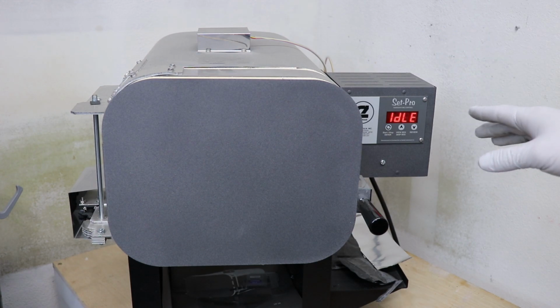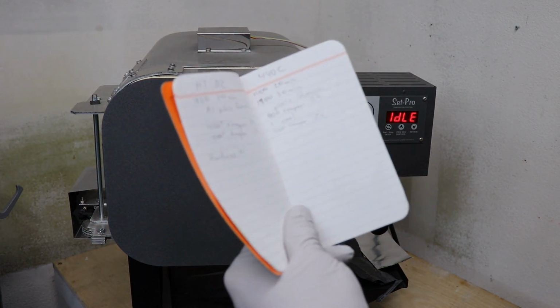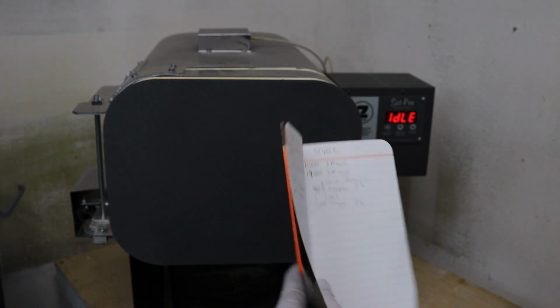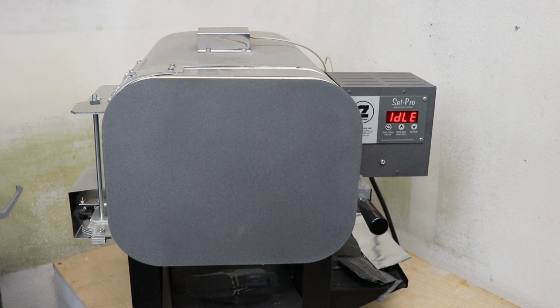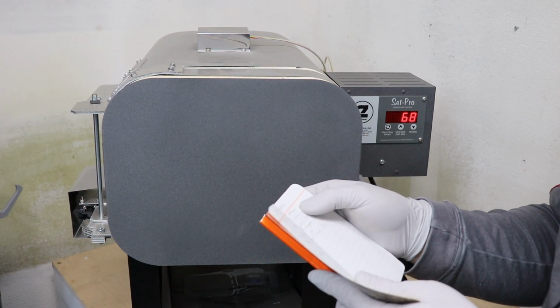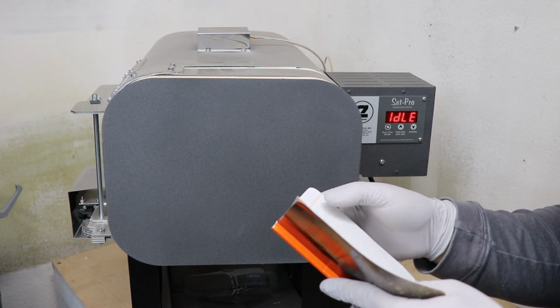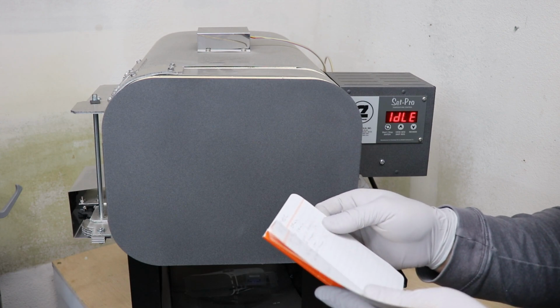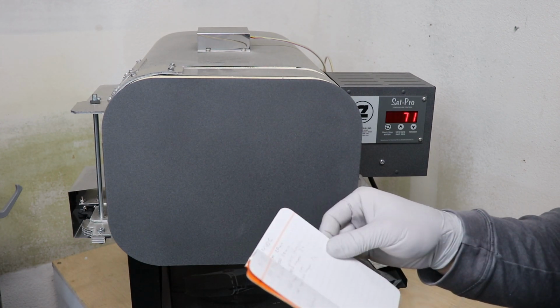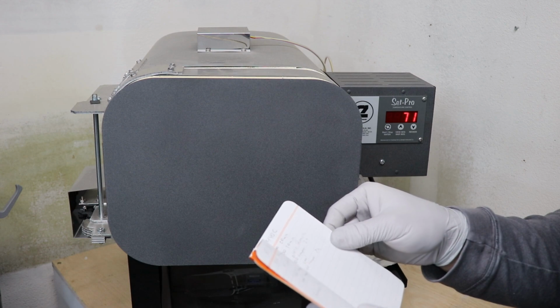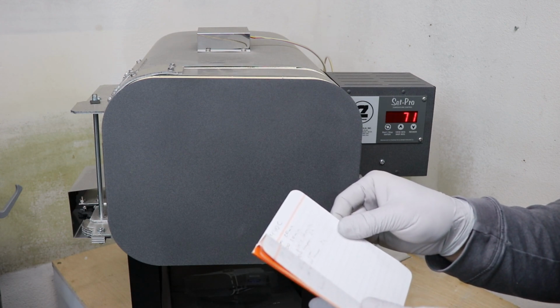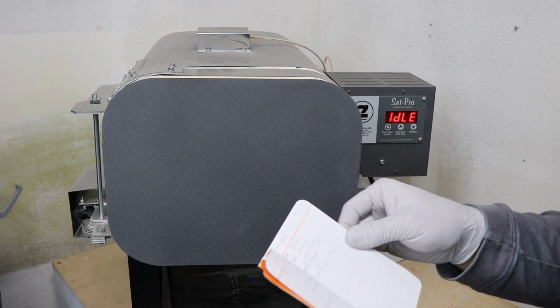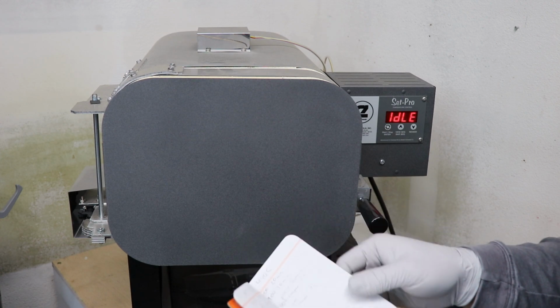Just got to set the controller up for the right temperature. According to my notes, which, you know, it's always a good idea to take notes when you're doing all these heat treatments, because your parts can vary from what the manufacturer of the steel will recommend. It'll be 1400 degrees for 20 minutes, 1900 degrees for 30 minutes. This is a plate quench, and then after that I can do 2 cycles of tempering at 400 degrees at 2 hours apiece. So it's kind of a long process.